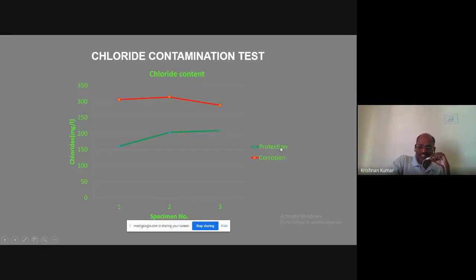After giving protection for all the three specimens, the chloride level is considerably reduced. This duration is taken just 24 hours. Within 24 hours, this much we are able to reduce the chloride level. It means if you apply the same thing to your existing structure, we are able to remove all the chloride. That is called electrochemical chloride removal.